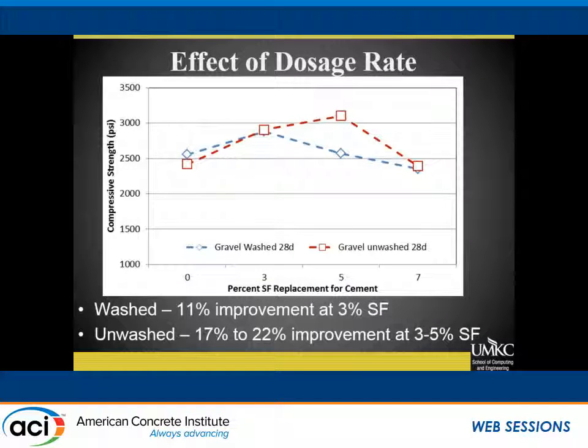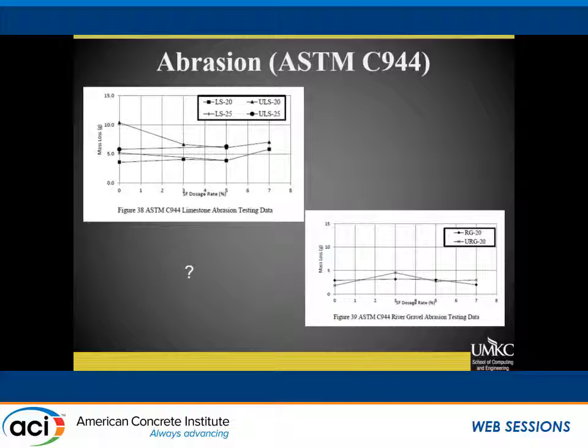For the river gravel, so this is kind of clean river gravel, washed and unwashed, not a whole lot of difference till we get to that 5% dosage, and then we actually had a substantial strength increase in the unwashed river gravel. So the material that was on it and the silica fume helped to give us a little bit better bonding. Abrasion, so on the left is ASTM C944, so that's the rotary grinding